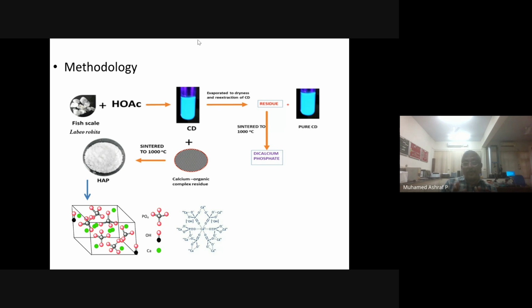Then this we again exposed, sintered to 1000 degrees centigrade, and we got beta dicalcium phosphate. So in this we have got three products. One is carbon dot, the second one is hydroxyapatite, and the third one is beta dicalcium phosphate. So in a single process we could manage to prepare these three products.